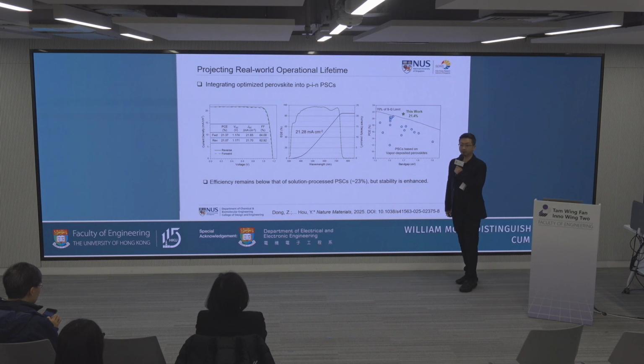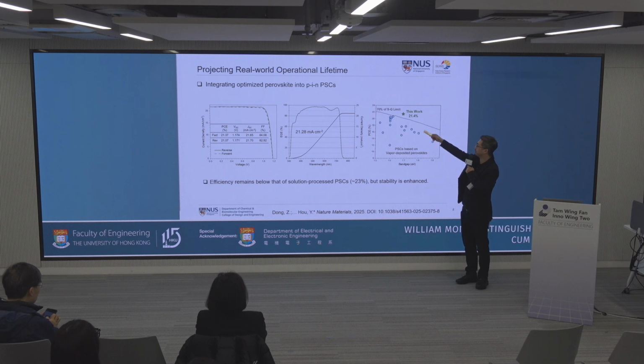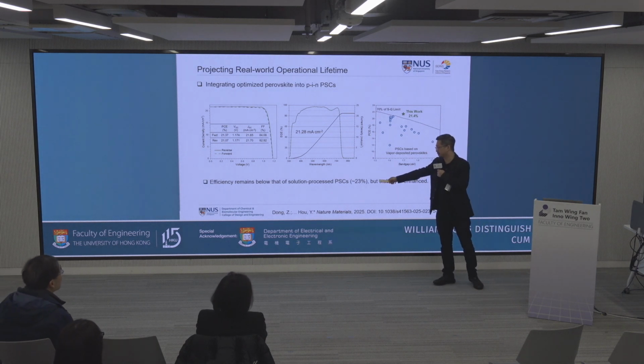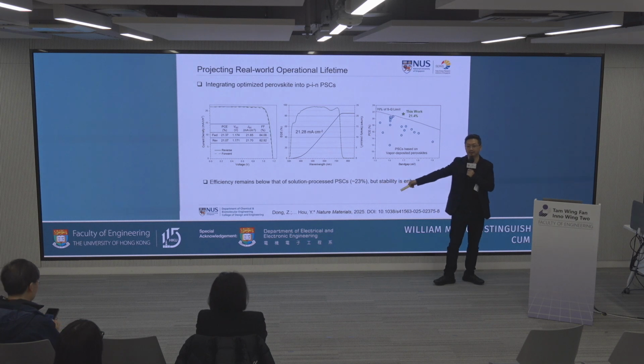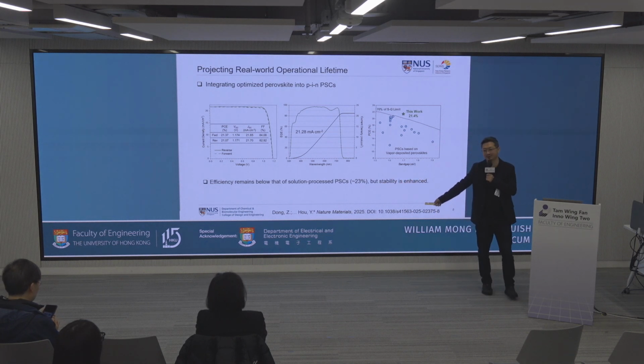And yeah, so this solar cell has okay efficiency because it is the wide band gap one. Its band gap is around 1.7. Its target is to match the silicon in the tandem structure. So therefore, efficiency is around 21. It's not as efficient as the solution process, which is currently more than 23. Yeah, some groups even report 24 already.